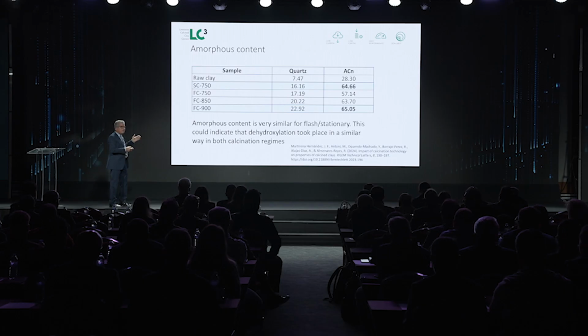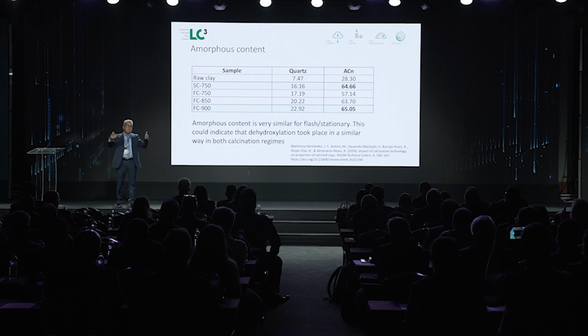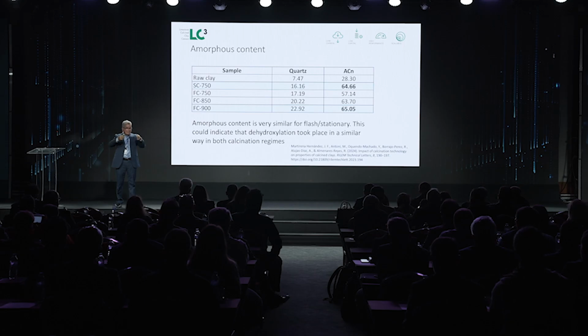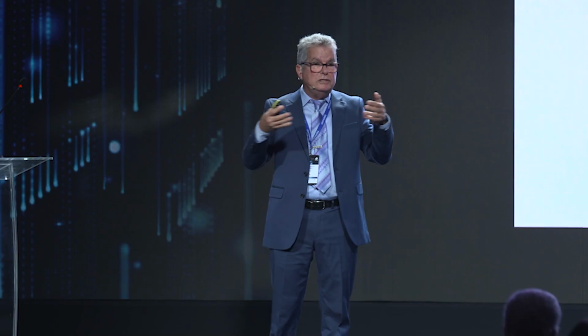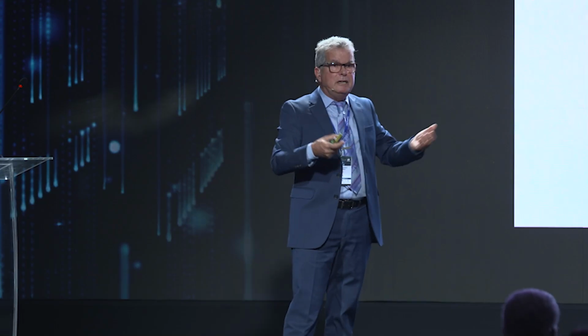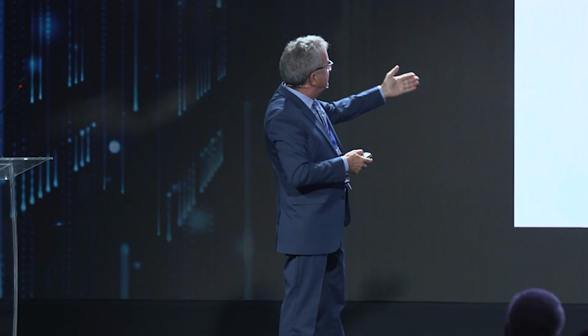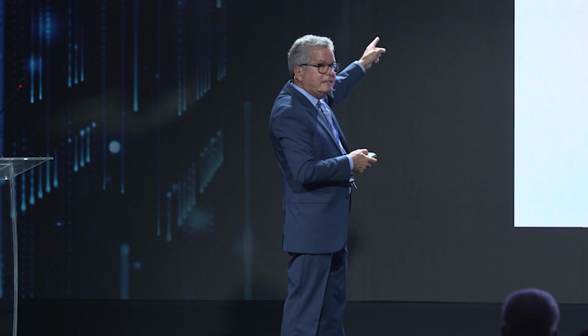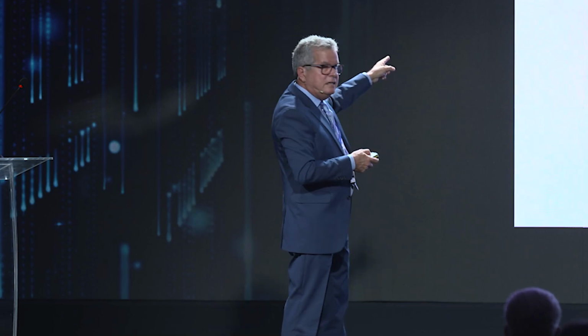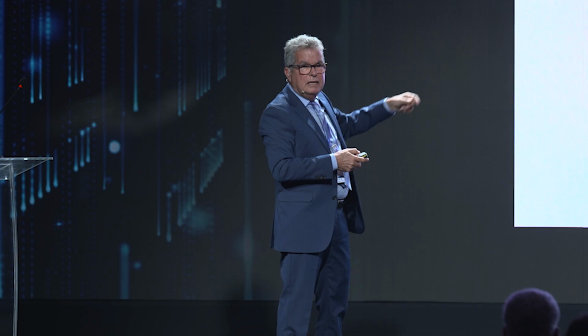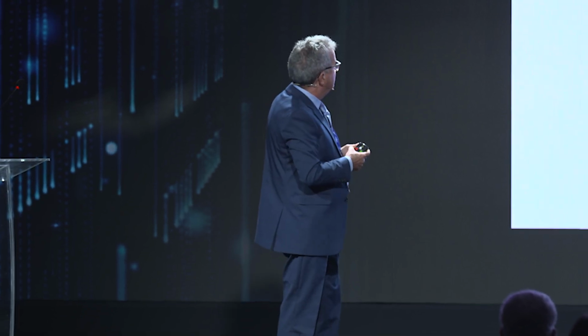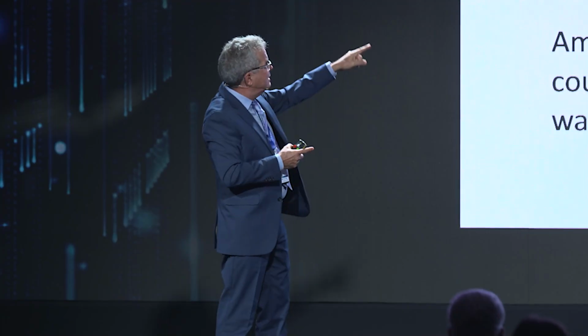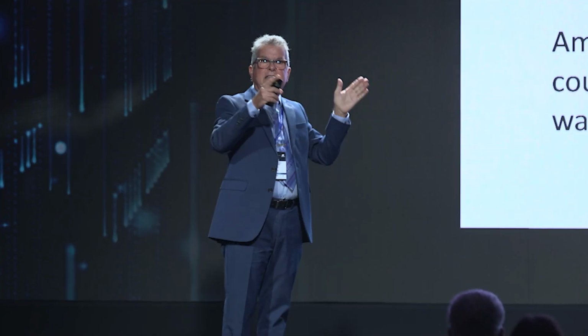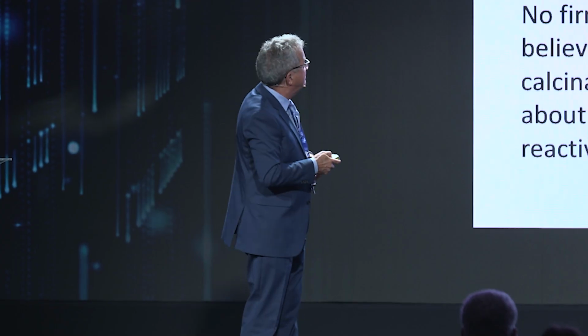What we did was an analysis. We took the same clay. We have pilot facilities for rotary, but also for flash. And we were able to prepare the same clay in the same way, and calcine the clay in the two technologies and compare the results to see if there was an improvement in reactivity. The first thing we realized, where you see static calcination, this is rotary, and then you see FC, this is flash calcination. The optimal temperature in flash was 900, and in rotary we were using 750, and we had the same amount of amorphous, which is more or less an indirect indicator of reactivity of the material.